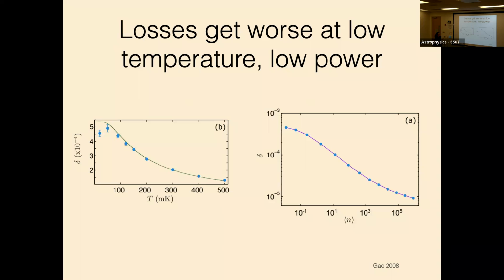This is now a plot of loss tangent as a function of temperature. And you can see that the loss tangent goes up with decreasing temperature. So that's bad, that's more lossy. And similarly, as I crank up the number of microwave photons I put in a superconducting resonator, the loss tangent also goes down. So there's something that I'm saturating. The general word people like to use to describe this is two-level systems. You have something that can saturate. So if I drive it really hard or thermally saturate it, then I don't see as much loss.